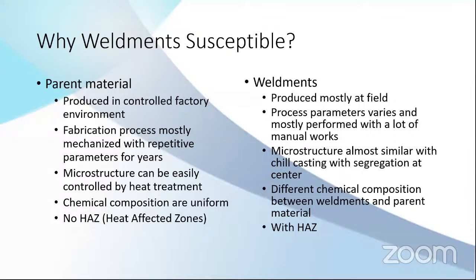Microstructures are not uniform. It's like a chill casting in combination with segregation of the chemical elements. And normally filler metals have a different composition from the parent material. So you can get a very different chemical composition between the weldings and the parent material. And the last one is that in the welding, you have heat affected zones. I'll explain later about the heat affected zones.